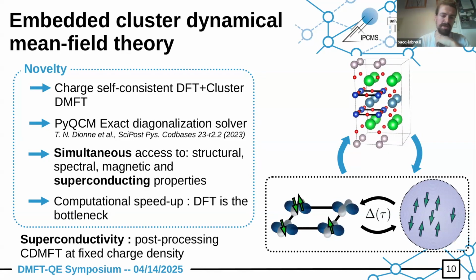Okay. And just for matter of detail, superconductivity is, so we do the charge self-consistency in the normal state, all right? We don't allow superconductivity to appear. And then at fixed charge density, we do a last cluster dynamical mean field theory calculation post-processing to see if superconductivity arises or not. And the idea is to say that superconductivity, for instance, the superconducting gap, is the smallest energy scale in the system, in the calculation. So it's okay to compute it later on as a post-processing at fixed charge density.